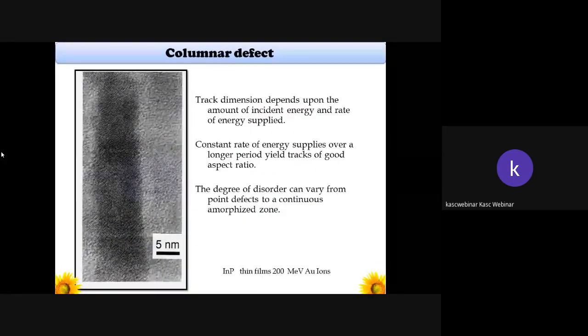In a columnar defect, I already said that there may be a recrystallization inside the trajectory of a material. During this recrystallization, once you have chosen the threshold amount of energy, like 80 MeV to 100 MeV of oxygen and argon ion, then the tracks or dimensions may differ.